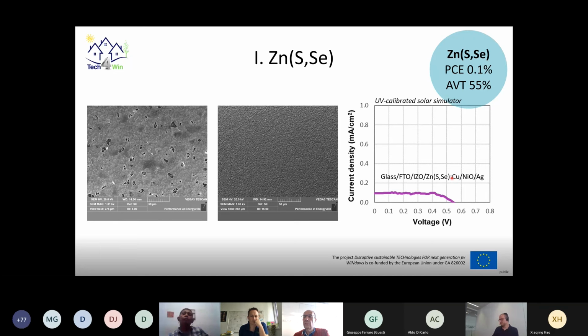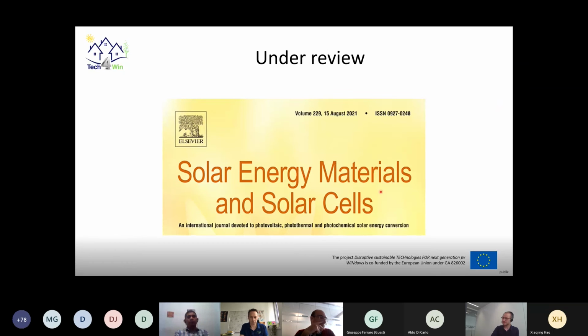So for this solar cell structure, FTO, IZO as a protection layer for the FTO because of the selenization, and then at the front, nickel oxide and a very thin silver layer, we're having this JV curve. Good news is we have a solar cell, but as you can see, the photocurrent is very small. But as you will see in the next part on the zinc oxysulfide, we see ways of optimizing this photocurrent. Still, where are we for the zinc sulfide selenide? We do have an efficiency of 0.1% for the moment, having an AVT of 55% at least. So at least it's promising, which has been submitted to Solmat and should be able to be read very soon, hopefully.